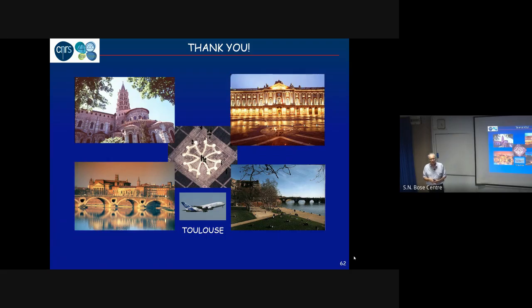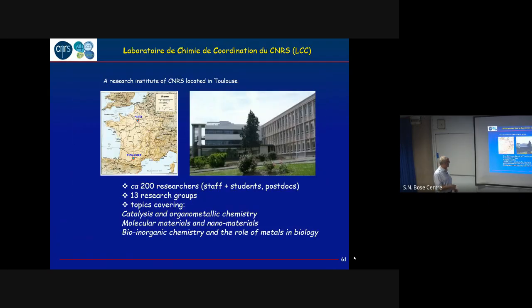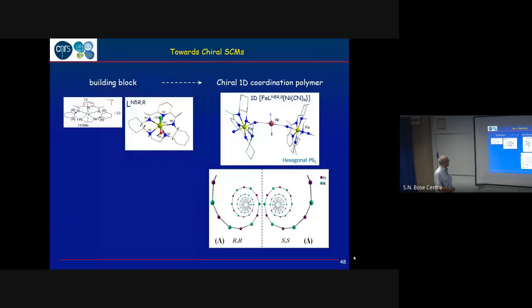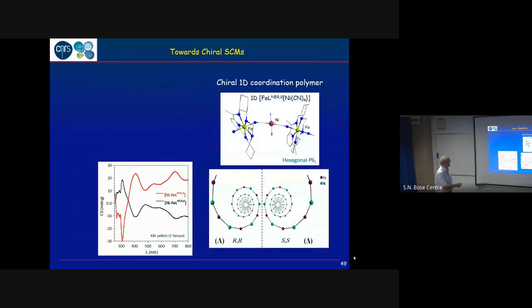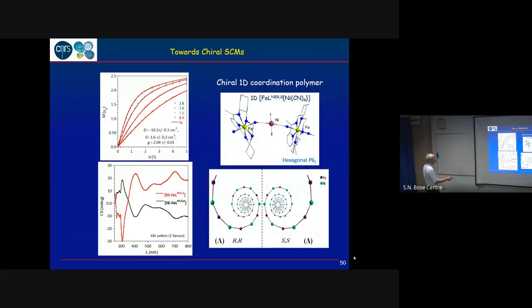So how do you experimentally measure D? Mainly from magnetization. What we do here, the dots are experimental data, and then we fit this data with a model taking into account the zero field splitting effect, and this gives you the D and the E parameter, the axial and the rhombic zero field splitting parameters. And when you get good fits like that, you know that your system is mainly governed by zero field splitting, and you get the right numbers. So today we mainly use that.